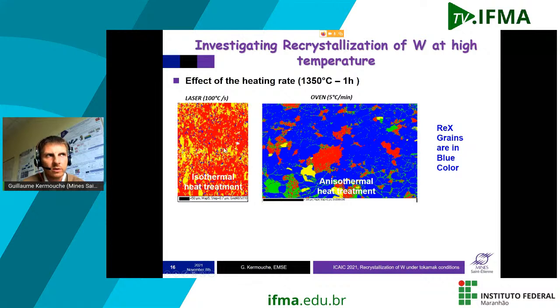You can see here the results of a heat treatment at a temperature of about 1350 degrees Celsius during 1 hour. Here is the microstructure at the end with the laser-based facility, so a fast heating rate. And here with the classical oven, at 5 degrees per minute. You can see here in blue the recrystallized grains. And here you can see that there are no recrystallized grains. So clearly, you won't get the same kinetics of recrystallization, because in this case recrystallization starts during the heating stage. So we have to use this kind of setup to go to very high temperature.